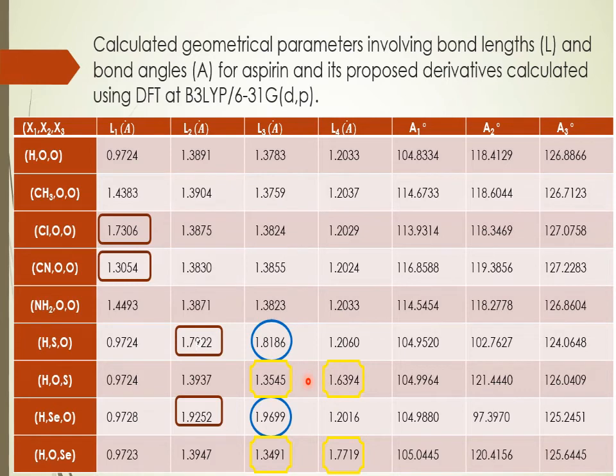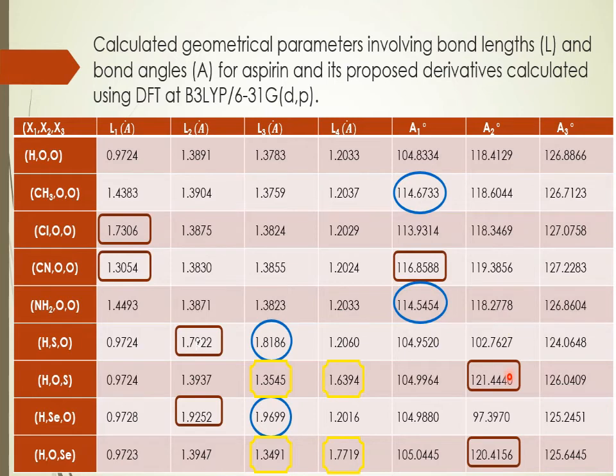In contrast to the results from L4, the sulfur and selenium in position X3 have the highest value compared to their results in L1, L3, sorry. Here, and from angle 1, the highest value is from cyanide, followed by CH3 and NH2. And here the highest value is from sulfur and selenium in position X3, and selenium in position X2 has the lowest value. And here angle 3 has nearly the same value in the whole column.